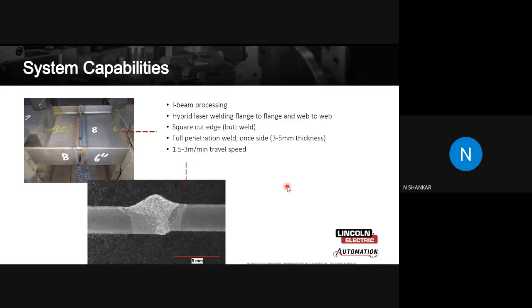So there is a minimum allowable limit set by the WPS actually, or your quality team will set an acceptable limit of pinholes in a zinc coated welded sheet because of the challenge that comes in. What is happening? All of us know that zinc vapors try to escape after the top material solidifies, so that it leaves a gap through which the gas vapor escapes, ending up in blowholes or pinholes. So those challenges can be addressed by having a specific solution with a waveform and a technique to do that. Similarly, hybrid laser also has got specific applications.